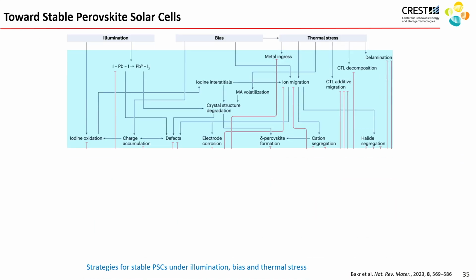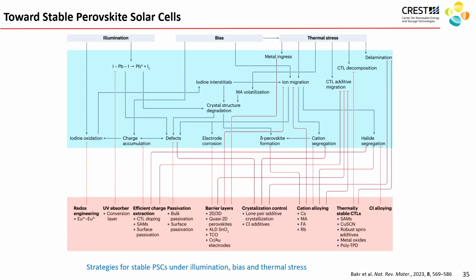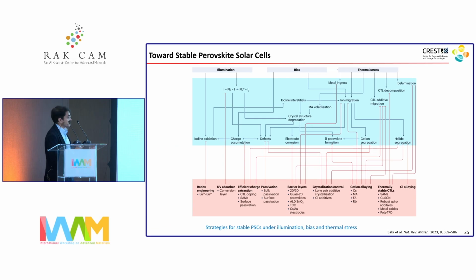Overall, just to give you an idea, in perovskites, typically when people measure stability, they look at either illumination, bias, or thermal stresses. Unfortunately, these stresses interact with one another, and when they do interact, they generate complex degradation pathways, and so really we need to study them together in order to create a solution that addresses the stability. In a real environment, you're going to face thermal stresses, you're going to be facing electrical biases, as well as UV and photo-generated stresses and degradations.